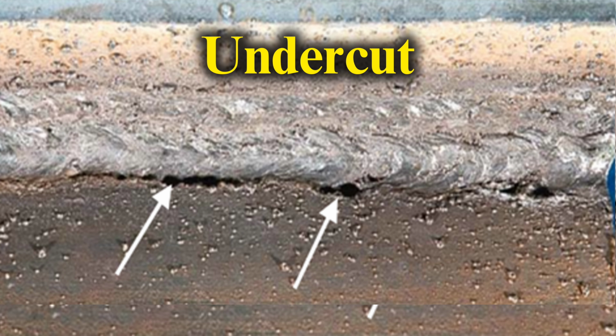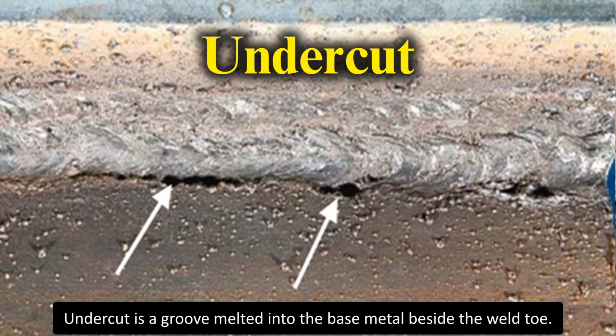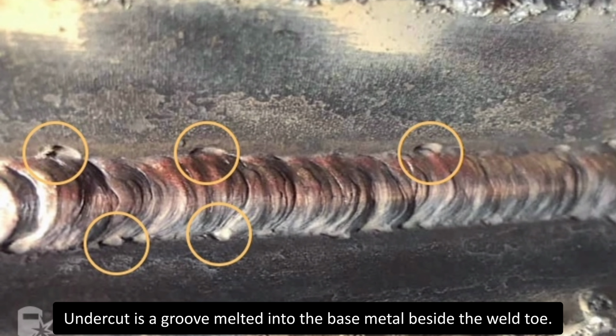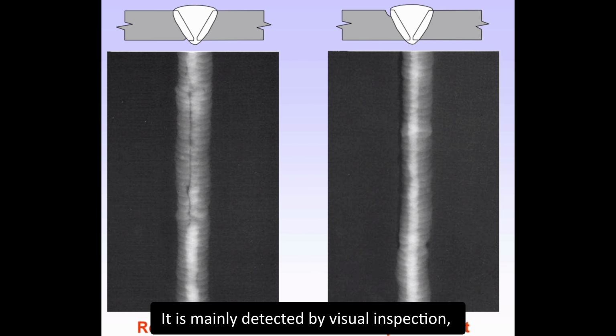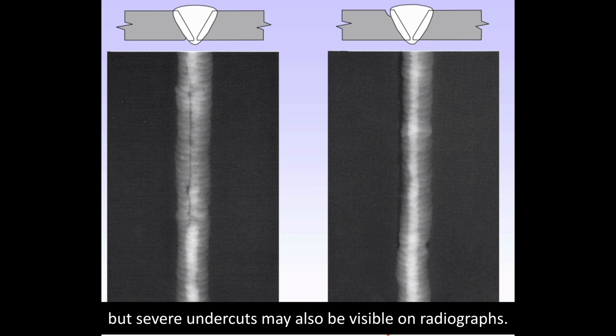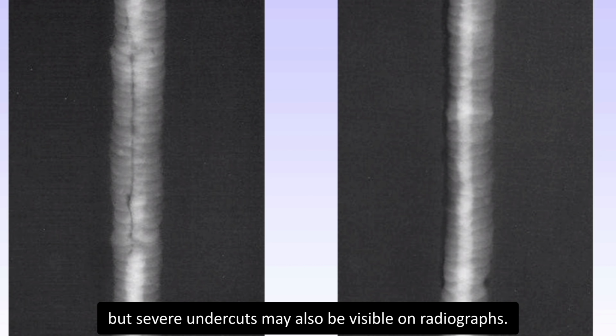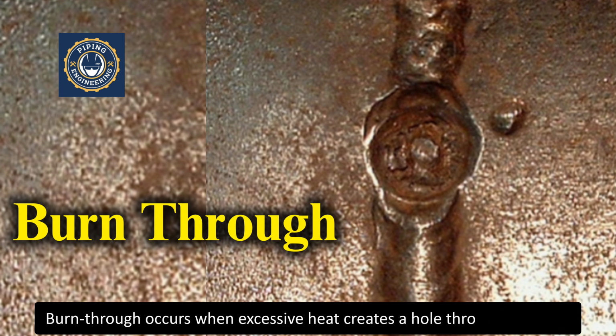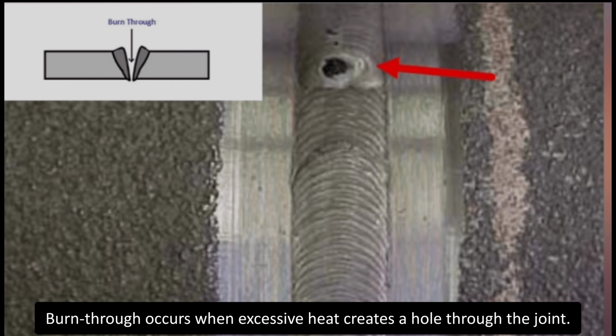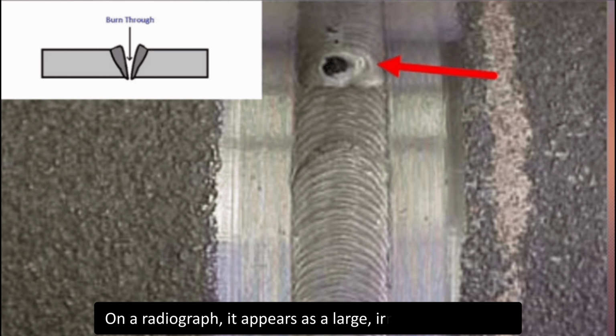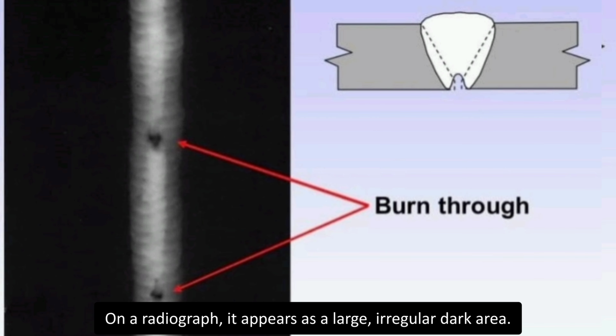6. Undercut. Undercut is a groove melted into the base metal beside the weld toe. It is mainly detected by visual inspection, but severe undercuts may also be visible on radiographs. 7. Burn-through. Burn-through occurs when excessive heat creates a hole through the joint. On a radiograph, it appears as a large, irregular dark area.